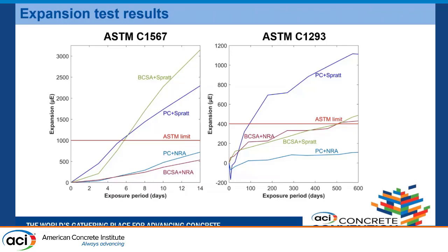Let's start with the non-reactive mixes, which are Portland cement and BCSA. Here NRA is non-reactive aggregate. We can see that the performance is good, in that they qualify the test. They are not ASR reactive. It's expected because they don't have reactive silica to promote ASR. And if we see the performance of the Spratt aggregates, which are known to be reactive, both Portland cement and BCSA show high expansion. One thing that is a bit surprising here is that the test shows BCSA having even more expansion than the Portland cement itself.